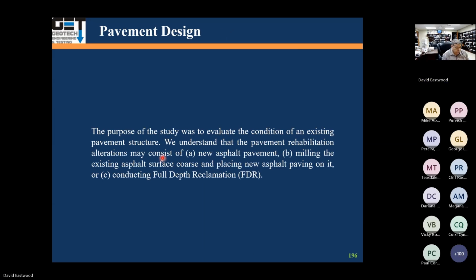So when we look at this pavement, the PCI, pavement condition index, was fair to very good. We want to know what the pavement structure was. We did the borings and found out the pavement structure was variable. One of the things we looked at, of course, is the future traffic loading. Based on that, we determine the type of repair: either reconstruction with new asphalt pavement, milling the existing surface and putting a new asphalt layer on top of it, or full depth reclamation.